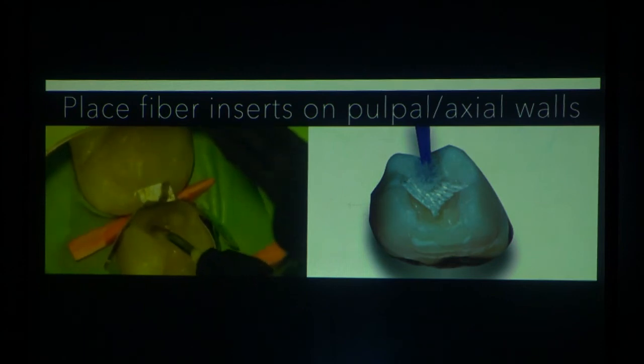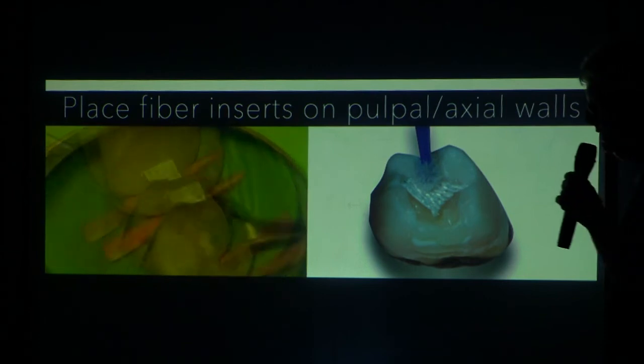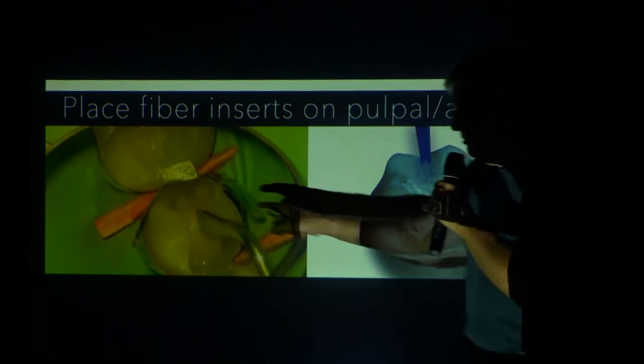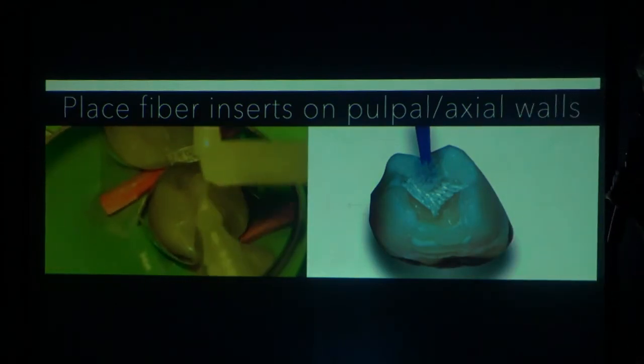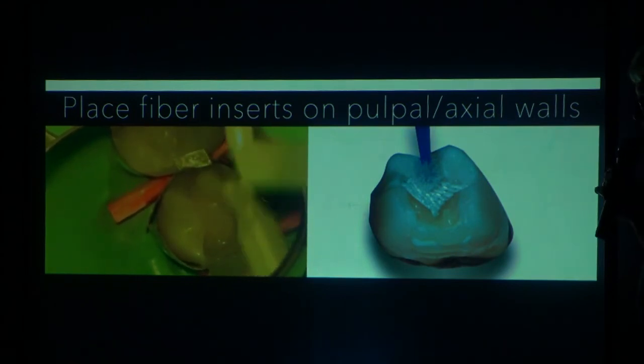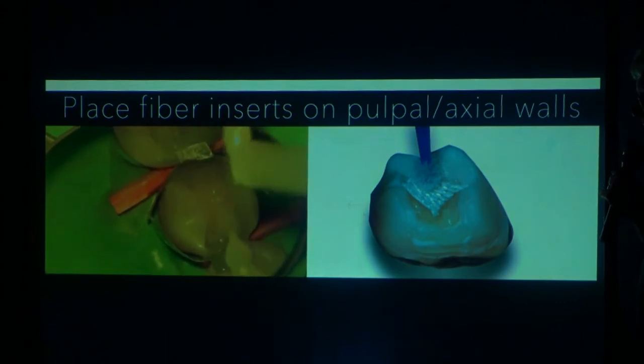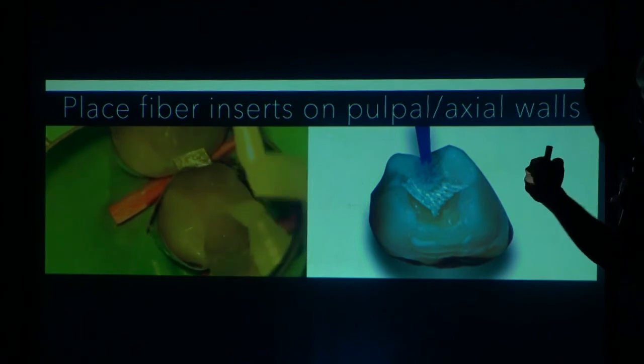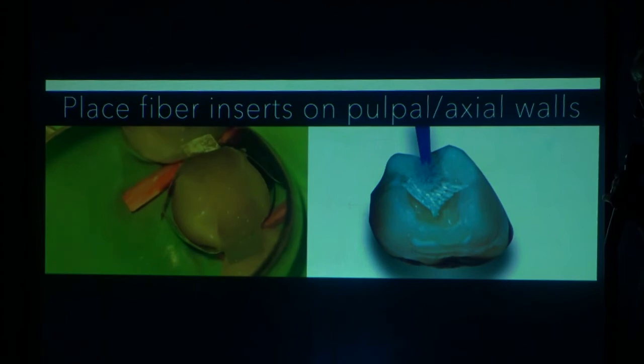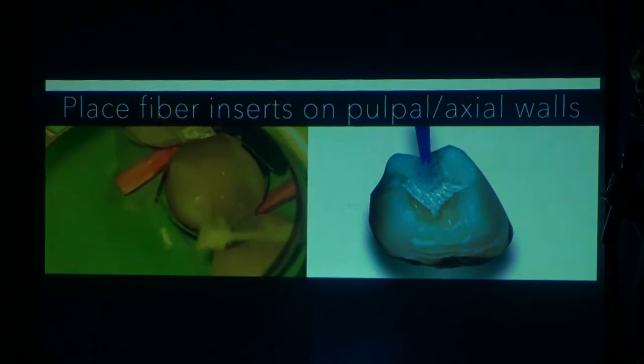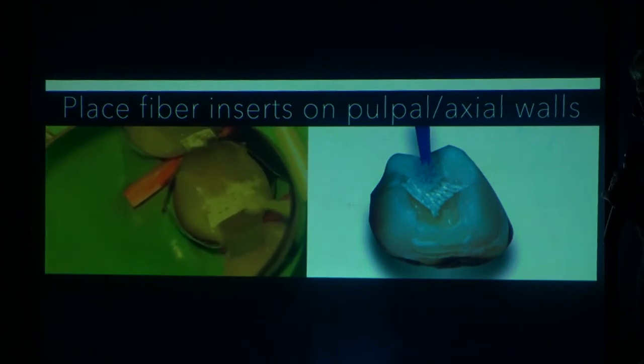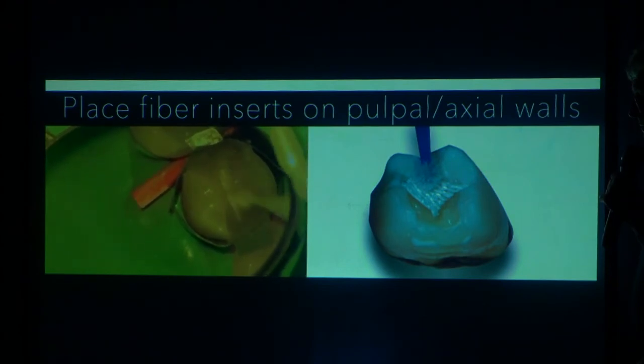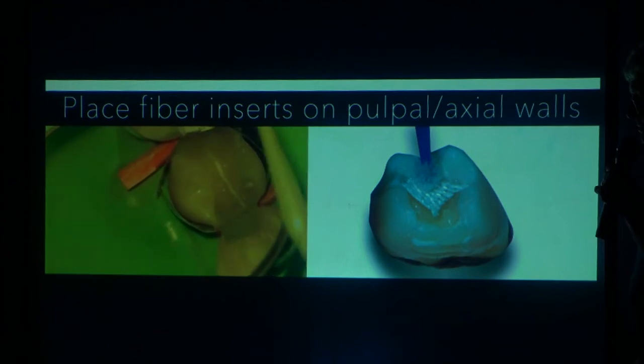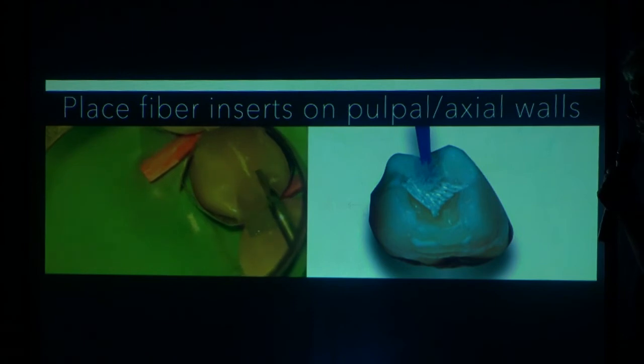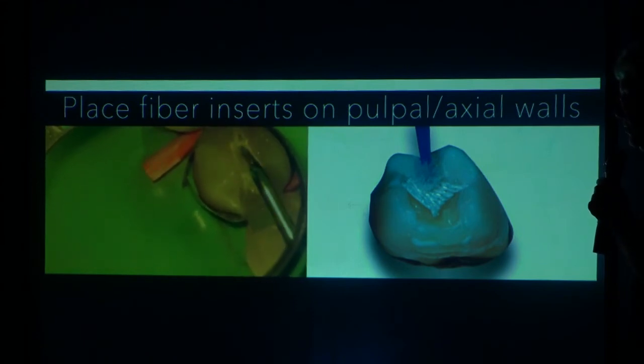Sometimes we put a little tab of flowable to help adaptation of our dentin replacing composite. You see that both of these shells have been created interproximally. When you create the shells, that takes time. That helps in the maturation of the bonds. Now, once you get the uncured composite at approximately 1 millimeter, that's the time to place your fiber, and the fiber can be placed in multiple pieces or in one piece in this situation. It will be on the pulpal and the axial walls. It takes a little time to do this, but that's all good because the time it takes you to place the ribbon allows the maturation of your hybrid layer.